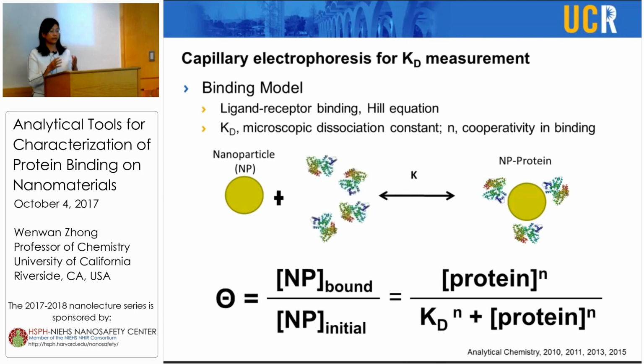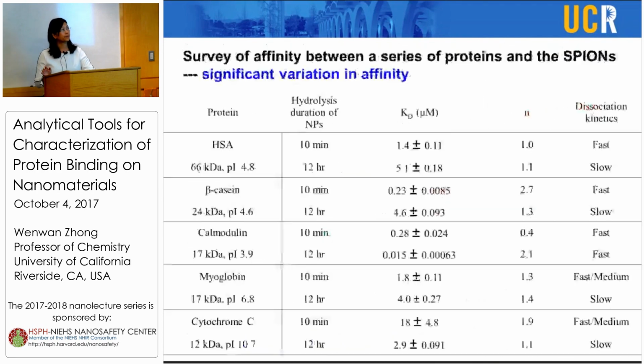Using that electrophoretic mobility change, we can fit it to the Hill equation to find out the binding affinity. Kd is the microscopic binding affinity here, and n is the cooperativity, showing how the proteins on the same particle affect each other's binding, whether it's a negative effect or a cooperative effect.